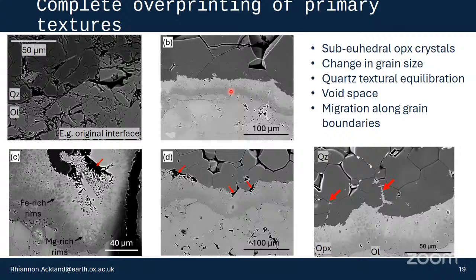The powders were sieved to be between 50 and 100 microns, but the grain size in the orthopyroxene is far smaller than this. You can also see that the quartz has recrystallized to be in textural equilibrium, with many examples of 120-degree boundaries of quartz grains. Obviously, they're opening up a void space, as I mentioned.